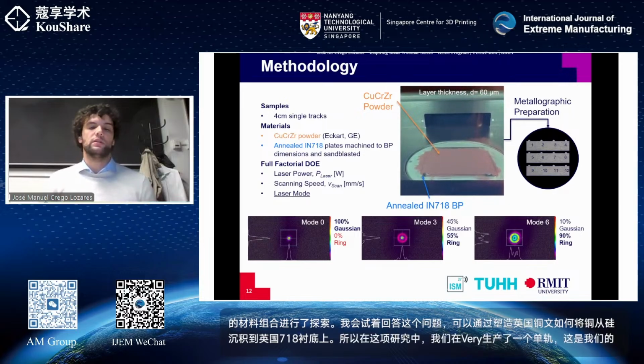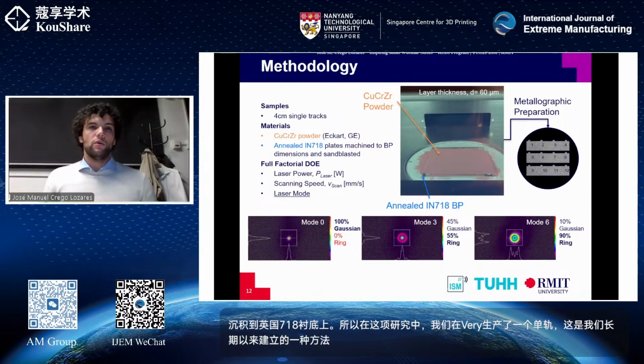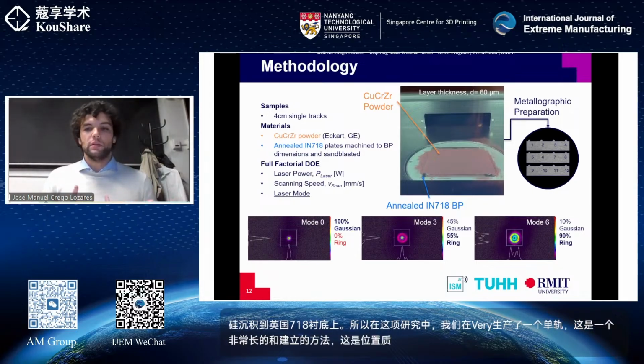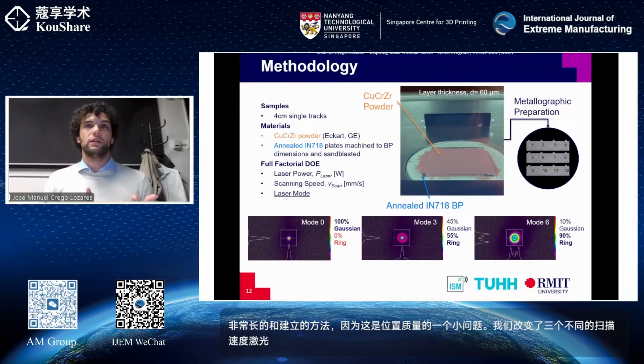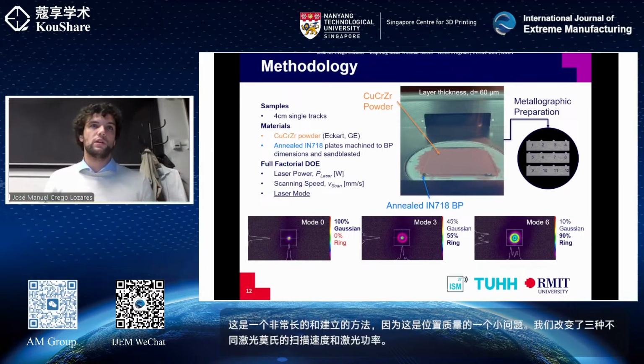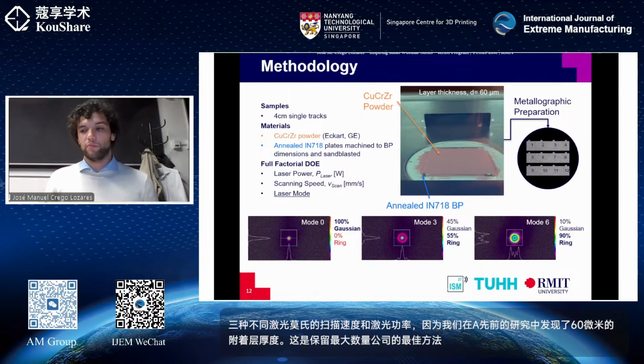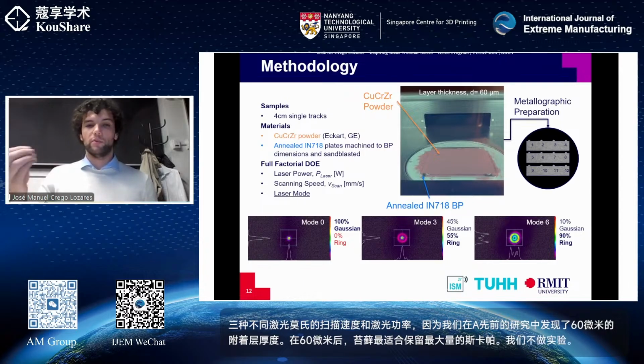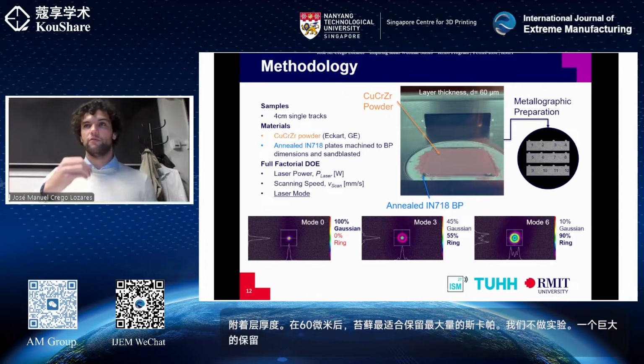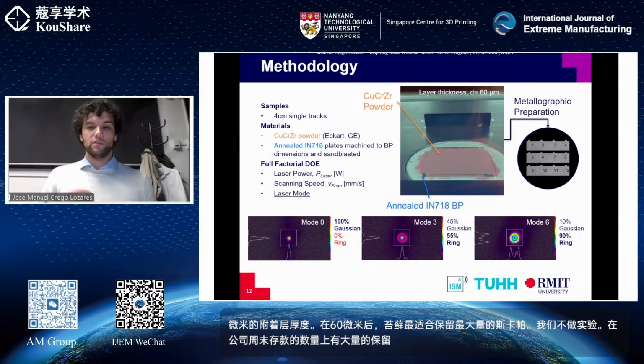We varied the scan speed and the laser power for 3 different laser modes at a fixed layer thickness of 60 microns that we determined in a previous study. That was the optimum for retaining the maximum amount of copper. After 60 microns, we don't see a huge retention in the amount of copper that we can deposit. We also fall into discontinuous regimes quite easily.